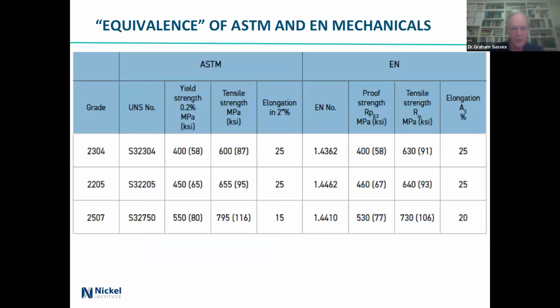What about the actual mechanicals, and what difference is there between ASTM and EN? And the short answer is not a lot. There are fiddling around the edges, but in terms of yield strength or 0.2% proof stress, tensile and elongation, not a lot of difference. Using A5 or elongation in 2 inches is just language. One thing about it is that the EN standards tend to have narrower ranges than the ASTM. So if you're ordering to EN and somebody supplies to ASTM, you just need to have a look and make sure that it actually will still fit.